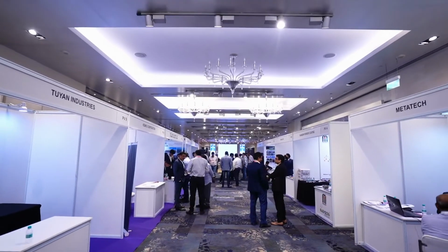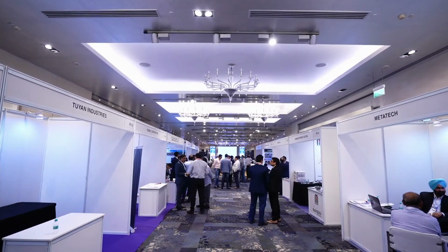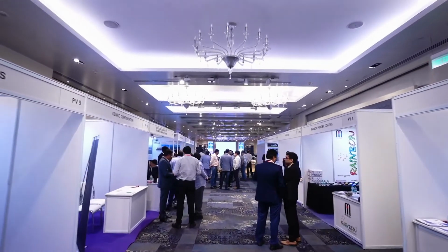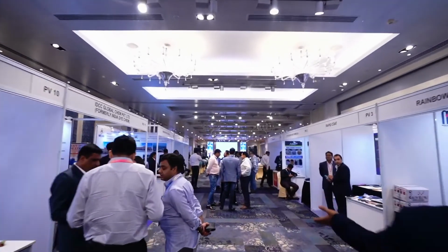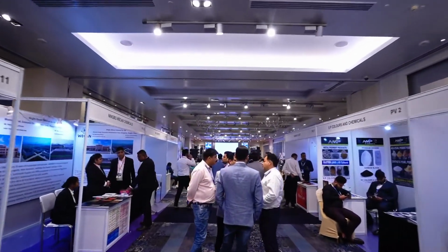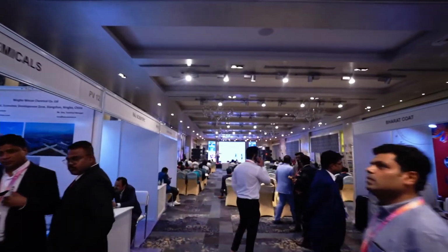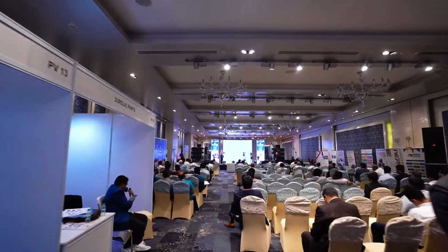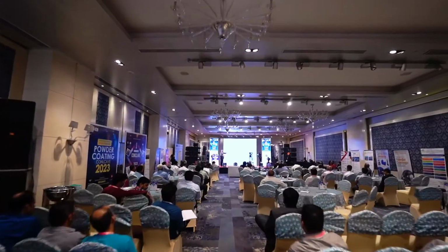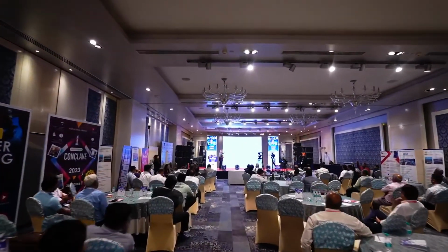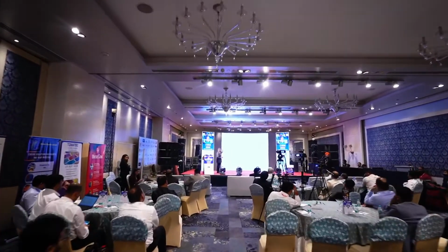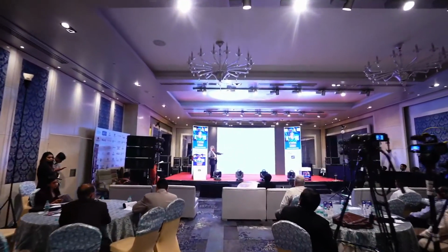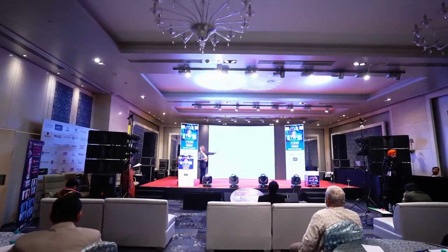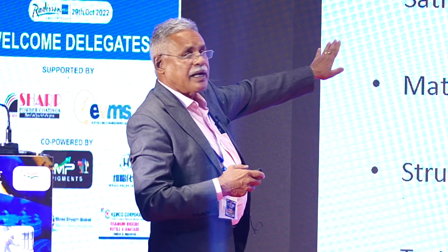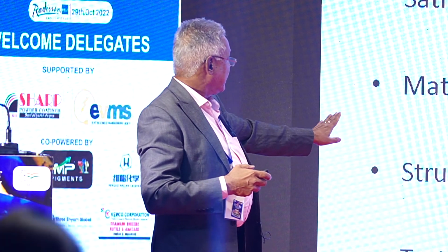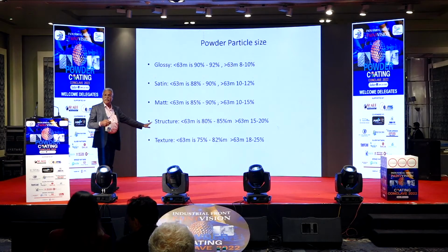Powder particles: अभी last slide में पंकज जी ने दिखाया है. Generally you cannot test all meshes every day, every batch, very difficult. We can keep 63 micron and test. उधर भी दिखाया है 95. If you see in 63 micron mesh, you will get around 10 to 15%. But different particles, different finishes, glossy, satin, matte, structure में थोड़ा अलग अलग होता है. जो structure and texture में ज़्यादा होता है 15 to 20%, 18 to 25%. ऐसा residue कम होता है, and that is the residue, and the rest of the material percentage will pass होता है in the system.